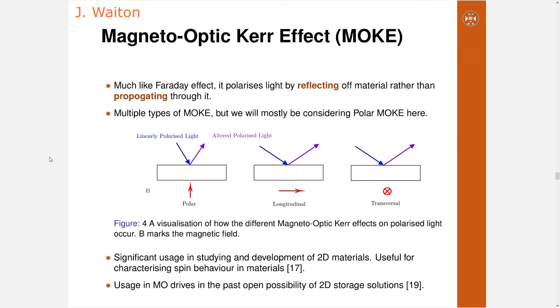materials. The MOKE is useful for finding information about the material's magnetic order and spin behavior, which helps us learn about the capability of certain materials for things like spintronic devices. Examples of this talked about within our paper are monolayer, which is meaning 2D, one layer, chromium iodide, and manganese phosphorus triselenide, which I will not pronounce again. Both have had their magnetic properties studied extensively with the MOKE and are found to have controllable magnetic properties to some extent. Beyond usage in the lab, MOKE has seen use in magneto-optical drives in the past, which have sadly fallen into irrelevance. The possibility of future 2D storage and processing devices based on this magneto-optical technology, using these newly researched 2D materials, will allow for small form factor and exceptionally dense information processing and storage devices.